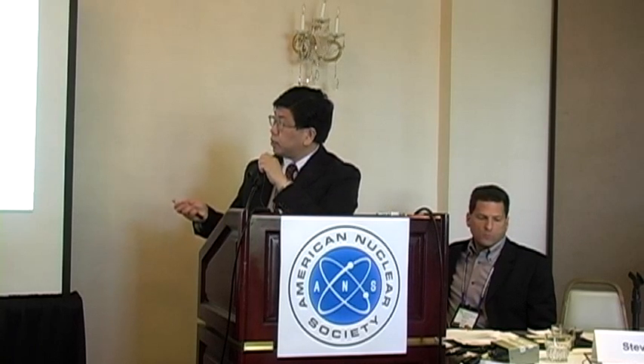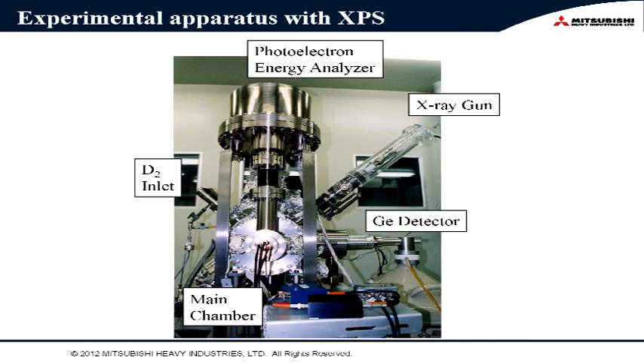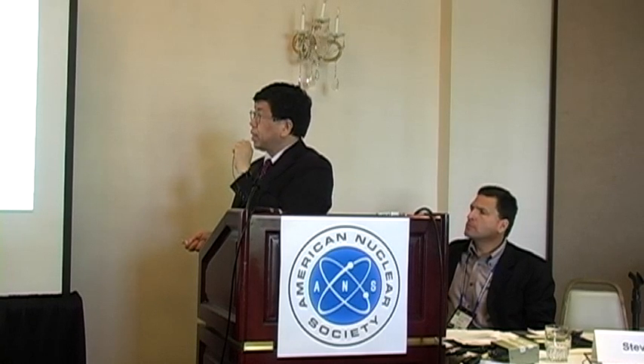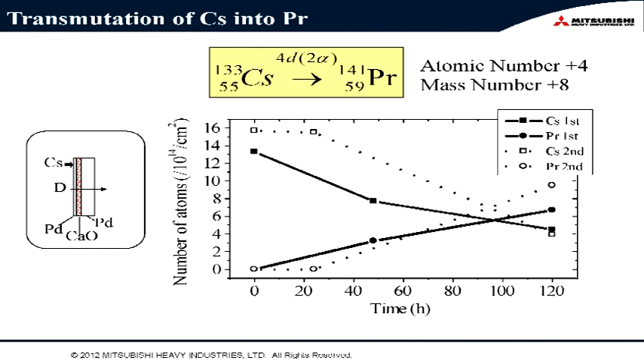This photograph shows the experimental apparatus with XPS. We put the sample with cesium in the chamber, and we measure by XPS, X-ray photoelectron spectrometry. This is the original apparatus. And this is an example of transmutation of cesium into praseodymium. At the beginning of the permeation, we have only cesium and no praseodymium. But due to gas permeation, cesium gradually decreases, and correspondingly praseodymium increases.